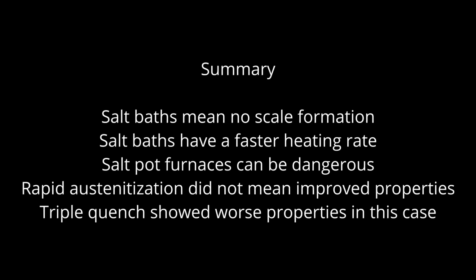So to summarize, salt bath furnaces, they have much faster heating rates so that you can spend less time heat treating. There are potential advantages to heat treating faster, but I did not see any. Using short soak times, rapid heating did not lead to an improvement in toughness. And somewhat surprisingly, using a triple quench led to a great decrease in toughness. Perhaps the grain size was finer, maybe it wasn't, but the main overriding factor was that we got extra carbon in solution, and that dropped our toughness.